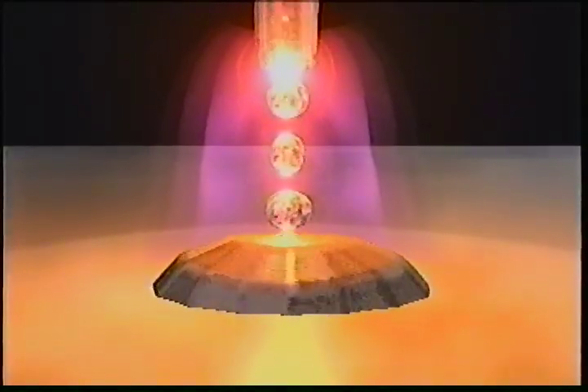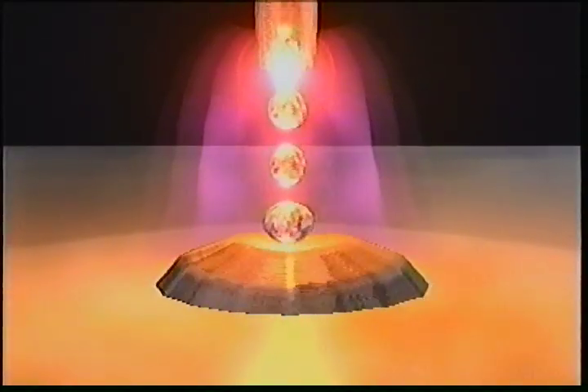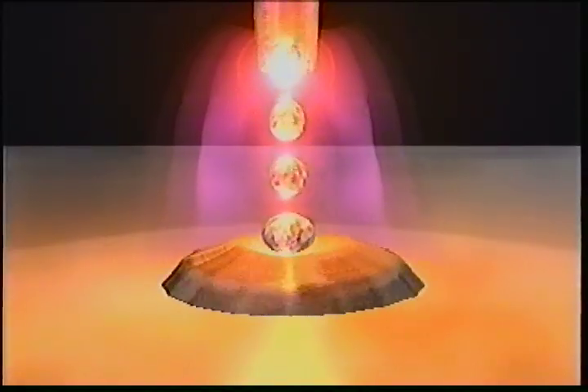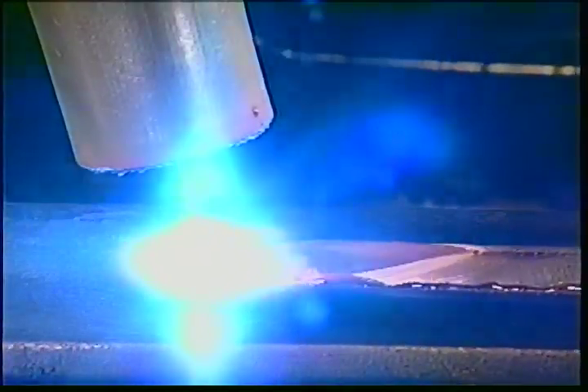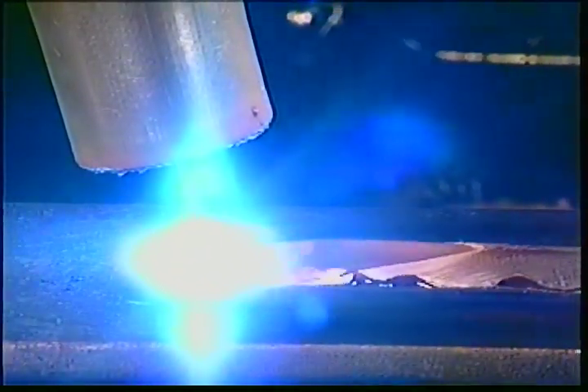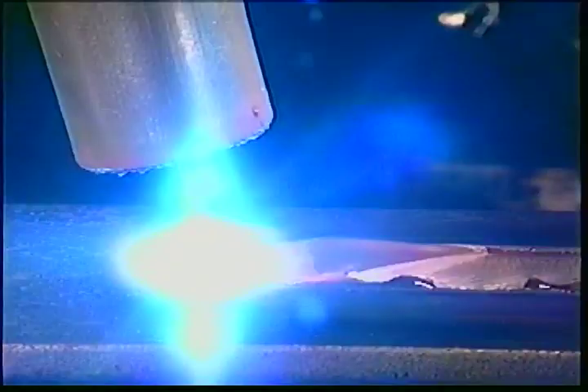A spray arc transfer sprays a stream of tiny molten droplets across the arc to the base material. The droplets are usually much smaller than the diameter of the electrode wire. Once the spray arc has been established, it is said to be on all the time. Spray transfer is achieved using relatively high voltage, wire feed speed, and amperage. When parameters are correct, the spray arc produces a humming or buzzing sound.